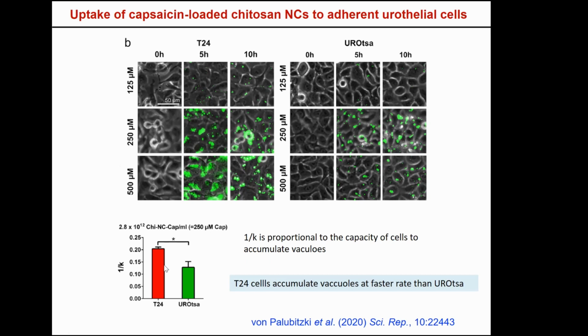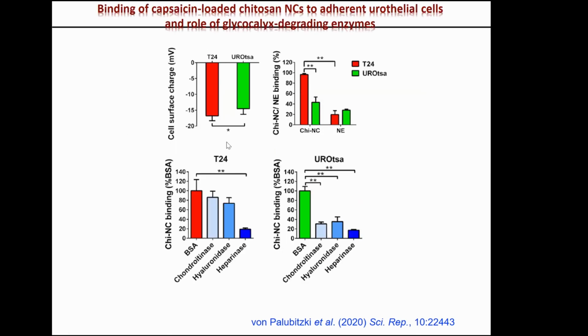And we can see that the rate of accumulation of the vacuoles is significantly higher for the T24 cell line. Now, we did compare also other biophysical characteristics of these two cell lines, including the zeta potential. And that's something we have done with bacteria also. By hypothesizing that, given that the nanocapsules are positively charged, they will electrostatically bind to cells, then by measuring the surface charge of the two cell lines, we saw that the T24 do have a slightly higher negative zeta potential than the Urotsa cells. And we can see that when also comparing the percentage of binding, it is significantly different between the two cell lines, and both of them much significantly higher than the nanoemulsions devoid of the chitosan coat.